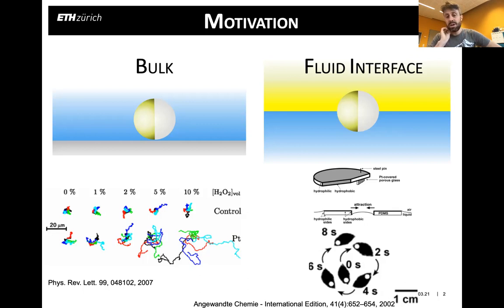and here they were interested in looking at the dynamic self-assembly of self-propelled objects freely floating and moving at an air-water interface. In this case, the swimmers that they made were significantly larger in size, but essentially consisted of PDMS, silicone elastomer plates, that had a porous platinum-covered, let's say, engine that was inserted into an aqueous solution of hydrogen peroxide. These objects were floating at an air-water interface, and again, the catalytic decomposition of the hydrogen peroxide by the platinum was responsible for the chemical gradients that gave rise to propulsion.